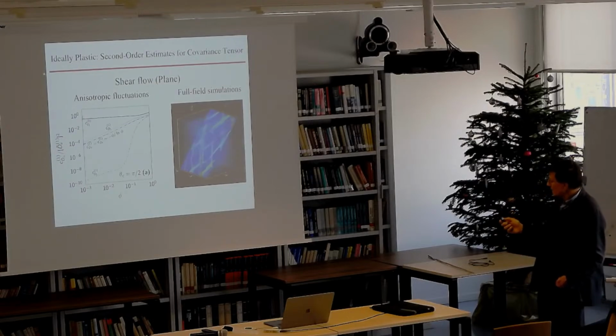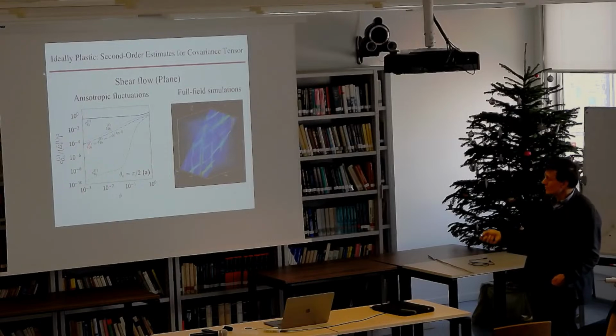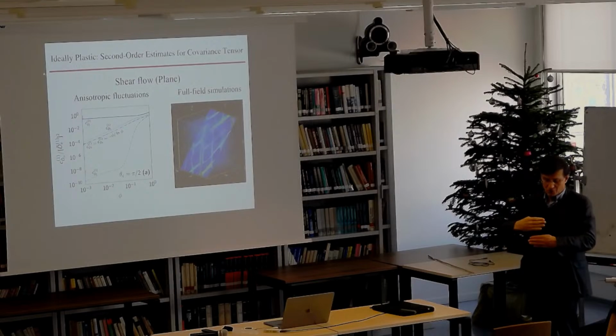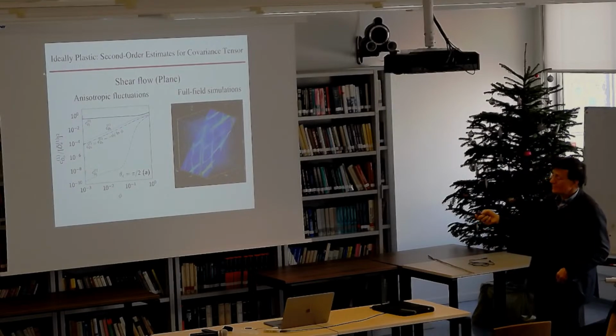You go to the shear case, and the distribution of the fields, being different eigenvalues of this fluctuation tensor, are hugely different, like 10 to the minus 10. So the fluctuations corresponding to going across the shear bands are finite, because you're integrating over delta functions, which gives a finite contribution. They don't decay—as long as you have particles, you have shear bands.